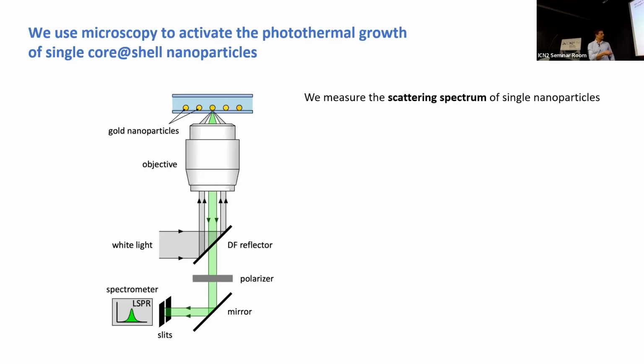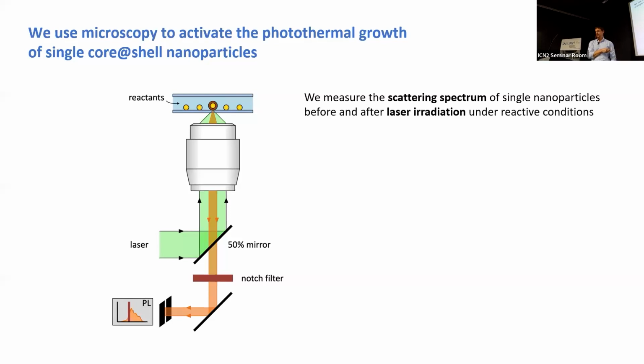But we can do more because we can switch from white light to a laser in the same setup. And now instead of doing this dark field reflection and hollow cone of light, we just put in a 50% mirror. We bring all the laser power onto the same particle that we took the plasmon resonance of. And we irradiate it when this nanoparticle is in a flow cell, and so we can put reactants into it. So we heat that very same nanoparticle for a certain amount of time. In this paper, we're doing 15 minutes of irradiation, and then we switch back and look at the plasmon resonance again.